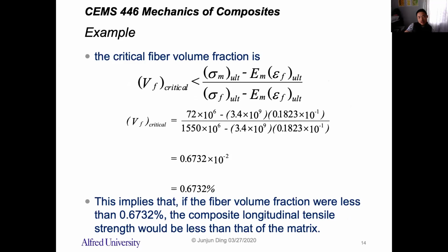So to calculate the critical fiber volume fraction, use the equation we just derived, and you can find the volume fraction is 0.6732%. It's also really low. So what does it mean? That means if the fiber volume fraction is less than this value, the composite longitudinal tensile strength will be less than that of the matrix. Here, the ultimate strength of the fiber is way larger than the ultimate strength of the matrix. So if you have a volume fraction of the fiber larger than this value, that means the composite tensile strength is larger than that of the matrix.